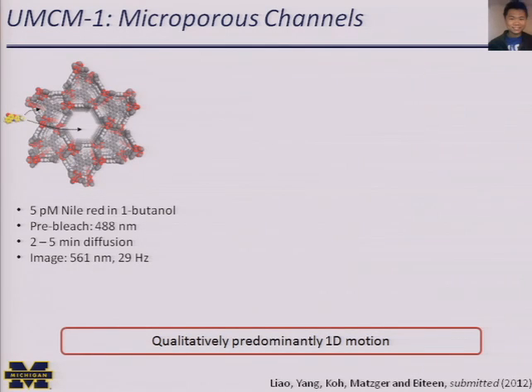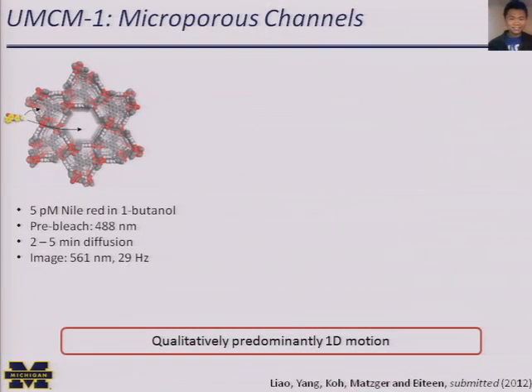So Yi incubated the materials in Nile red and then pre-bleached them so that there wasn't too much background, partly from these leftover metal centers that could be there from the synthesis, and partly just from having too much Nile red. He then waited 2 to 5 minutes for new Nile red molecules to diffuse into the crystal. And what he pointed out to me that was very exciting here is that experiments that have previously been done on porous materials with fluorescence had the fluorophores baked into the synthesis. But here what we're doing is actually introducing guest molecules that will really mimic things like storage, where the molecules have to come in from the outside.